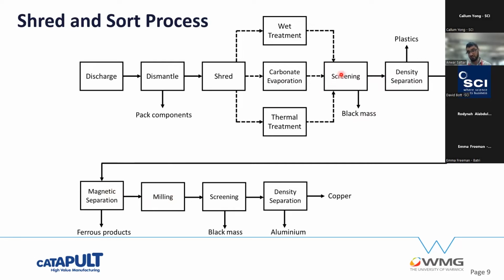In the first screening stage, you've still got a lot of the cathode and anode material, the powder that you want, stuck to the foils. And so in the milling stage, you mill it so that you take more of the powder off. You then do another sieving step to get more of the black mass. And then finally, you do your density separation. You can separate the copper and aluminium.